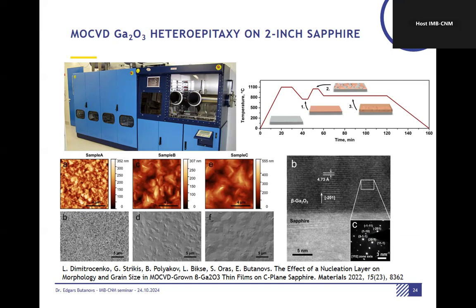There are these large grains. However, there are small angle grain boundaries, which really kind of ruin the electrical properties of the material. We worked on developing different buffer layers or different nucleation layers, similarly as was done back in the day for gallium nitride growth on sapphire, to induce these kind of thicker buffer layers, and in the end you have a real device layer, which has much fewer threading dislocations, etc.